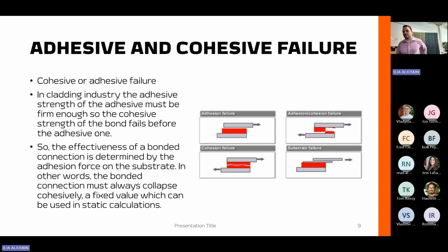Of course, there are a couple of other types of failure, when there's a combination of adhesion and cohesion failure. It could be that, let's say, half of the surface area that your adhesive was attached to was dirty, so that caused adhesive failure and then cohesive failure in the middle. And then there's also substrate failure, if the actual materials that you're attaching are weaker than the adhesive, which does happen sometimes. That's a more positive failure because the adhesive is stronger than the material.